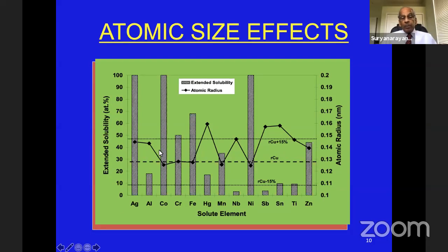Now, if you looked at any of the solid solution formation cases, Hume-Rothery had suggested that you can have solubilities limited by two different factors. One is the atomic radius and the other is electronegativity. Of course, valency also plays an important role, but let us look at only some of them. If you plot the atomic radius on the y-axis against the solute content, you would see that if you looked at copper as the solvent, plus or minus 15% are the limits suggested by Hume-Rothery. This is plus 15% of the atomic size. This is minus 15% of the atomic size.